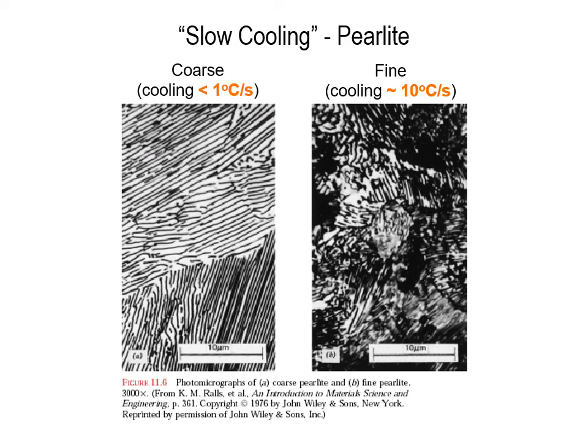So what is the difference between coarse and fine? Well, with slow cooling we see pearlite, so we have coarse pearlite here, which is cooling at less than 1 degree per second, and fine pearlite is cooling at approximately 10 degrees per second. We can see the difference in these structures in the photomicrographs. A on the left-hand side is our coarse, and B on the right-hand side is our fine structure. And you can see this is the same scale on both, 10 microns.